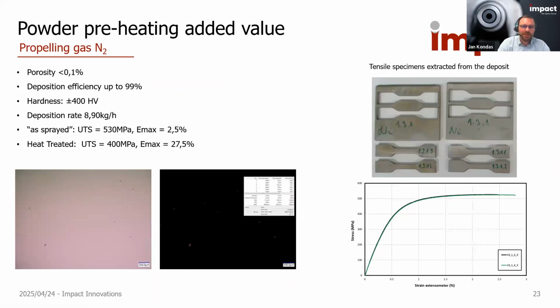This powder preheating added value is, for example, shown on this nickel deposit, where we achieved depositing pure nickel with nitrogen process gas maximum parameters with powder preheating. We are working with a deposition efficiency of 99%. We're reaching almost zero porosity. And as you can see, the tensile properties are around 530 megapascal, or close to 530 megapascal UTS, and a bit over 2.5% ductility.